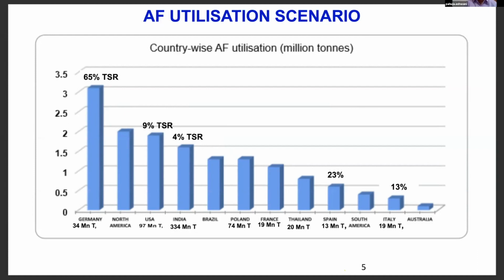So in terms of quantity it is fairly significant, not that bad a scenario, but in terms of percentage, because of the high capacity of the Indian cement sector, the percentage is low at 4%, and a lot needs to be done in the field of alternate fuel utilization enhancement. Next slide, please.